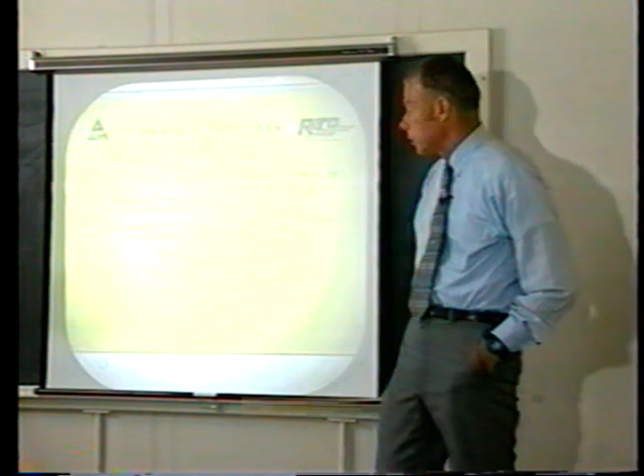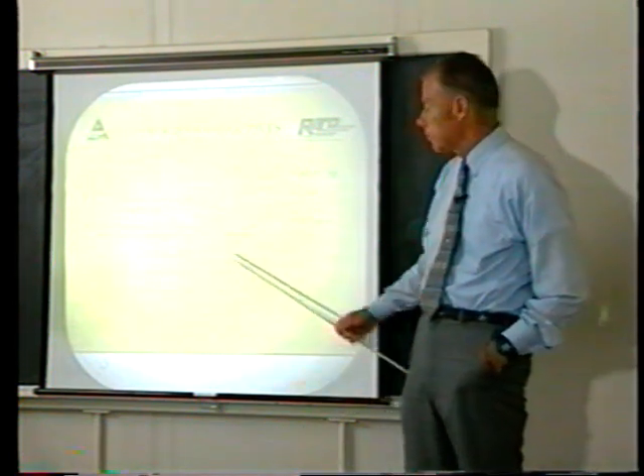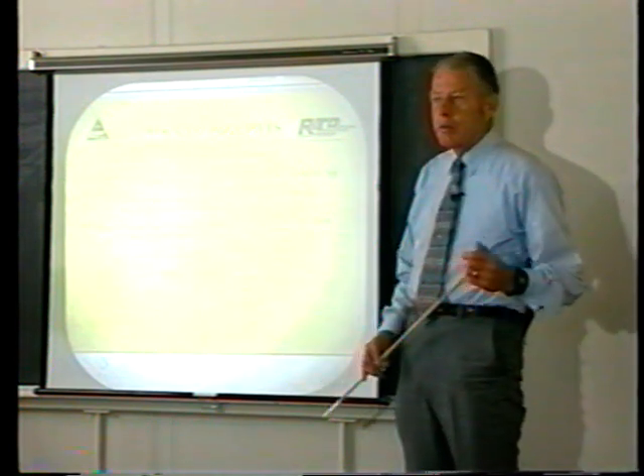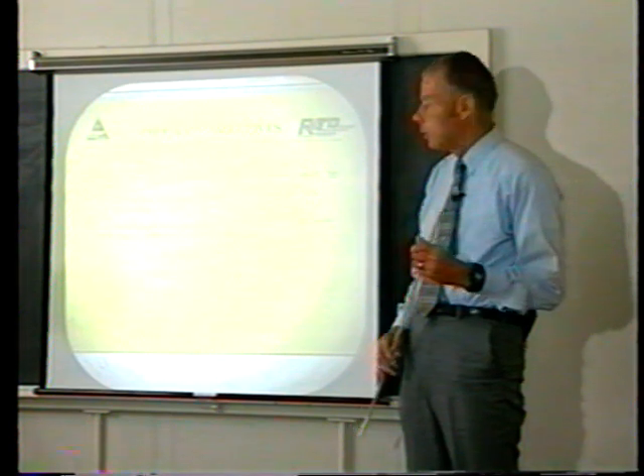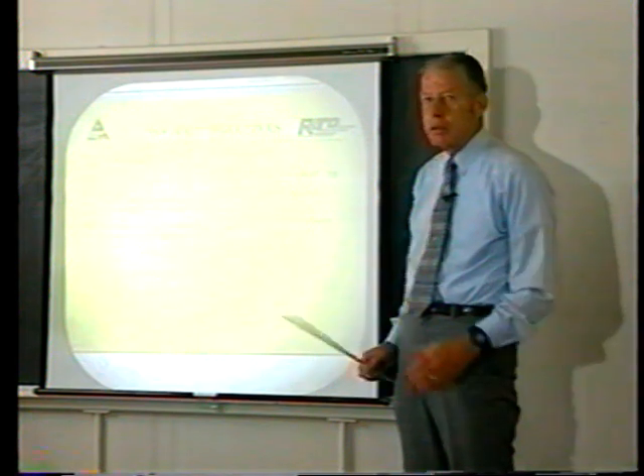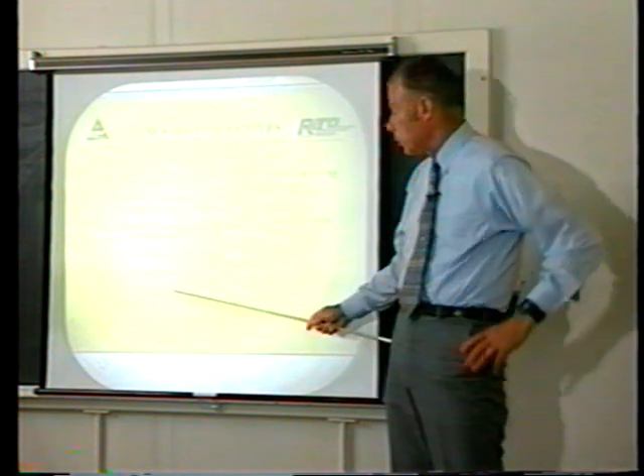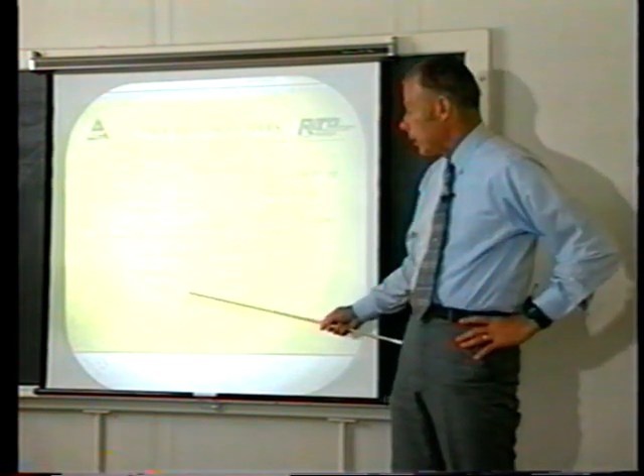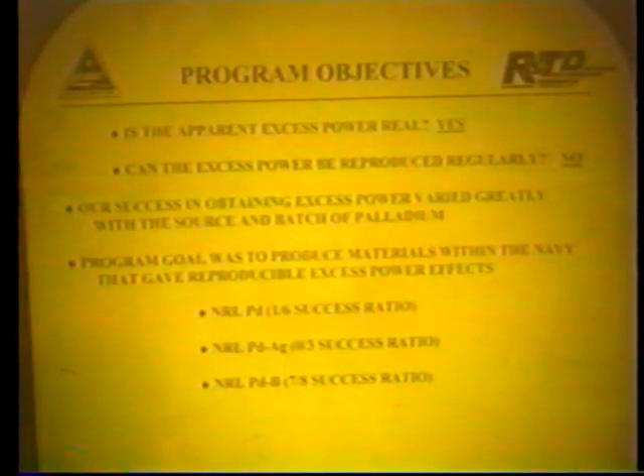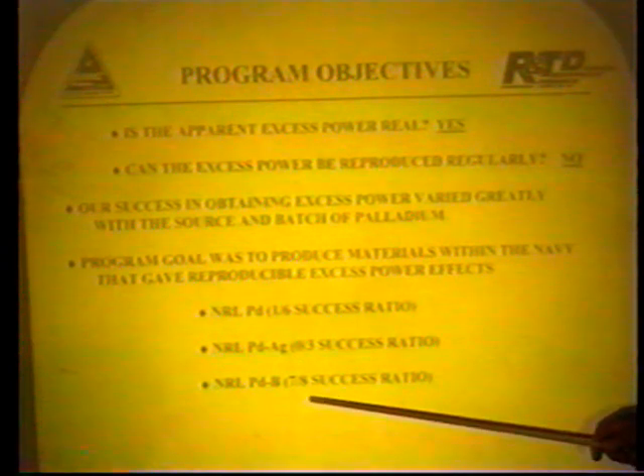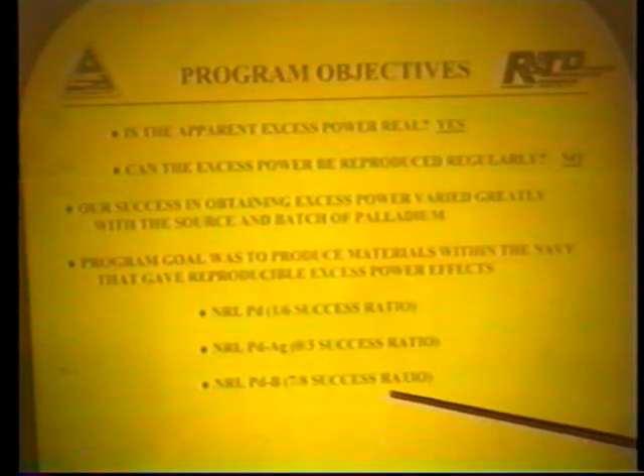Our first studies concerned palladium made by the Naval Research Laboratory, but our success rate was quite poor. Only 1 out of 6 experiments at our laboratory gave excess heat using palladium. We then tried palladium silver alloy and did not have any success with that alloy. No experiments out of 3 gave excess heat. Towards the end of the program, we did have success with the palladium-boron alloys. At our laboratory, 7 out of 8 experiments with these alloys gave excess heat. 7 out of 8 was the highest success ratio that we had with any type of material.